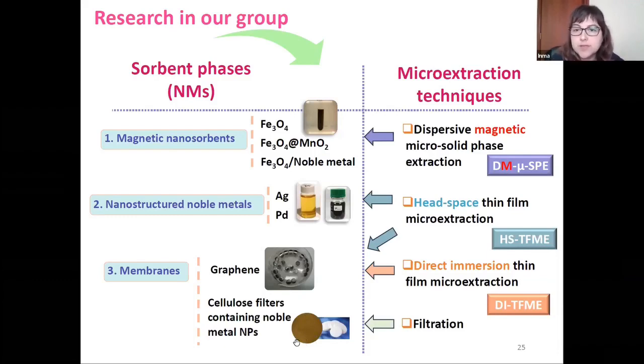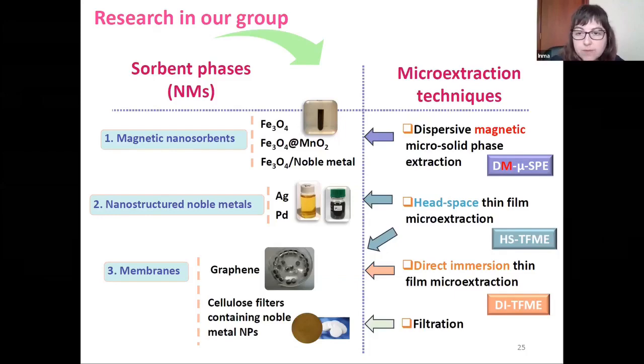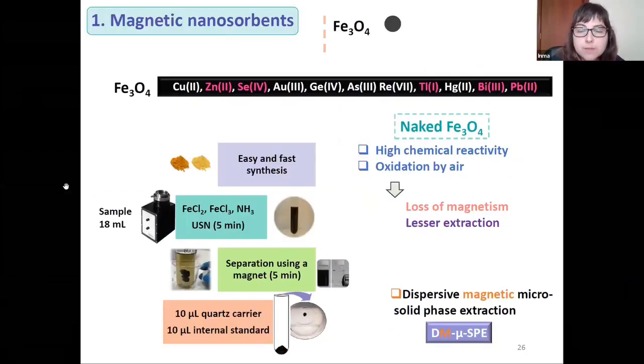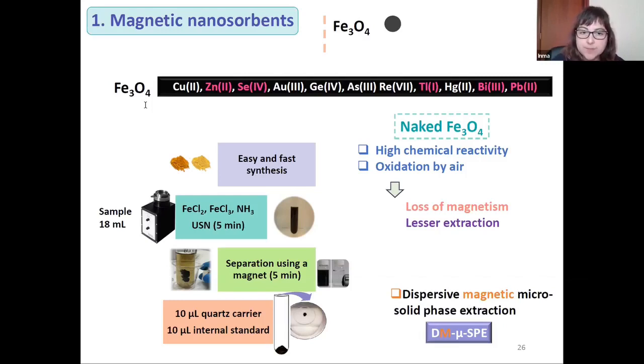And we use different microextraction techniques: dispersive magnetic microsolid phase extraction for these magnetic nanosorbents, and then thin film microextraction in both modes, headspace and direct immersion. And in the final work, we use filtration. We developed here an in situ sonochemical synthesis of magnetite in the presence of the sample solution containing all of these target analytes. In this case, it is very interesting because we integrate all the steps in one. It means we perform the synthesis of nanoparticles while simultaneously we preconcentrate the target analytes into these magnetic nanoparticles.